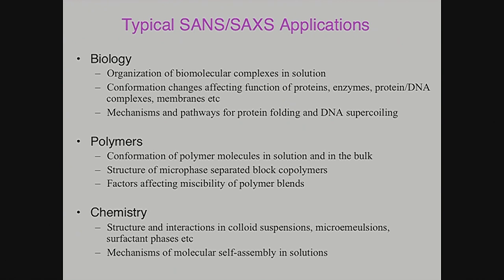So the fact that you had 98% hydrogenated polymer and 2% deuterated meant you had a huge background. After they figured out that that wasn't the right way to do it, they used 98% deuterated polymer and 2% hydrogenated polymer. Pretty obvious now, but wasn't back in 1972.